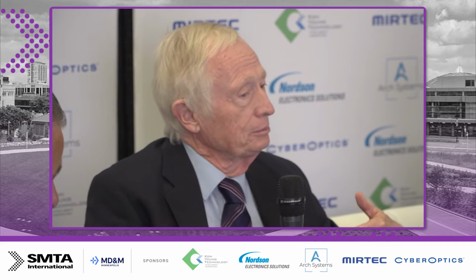And that's just really to establish the benchmark of where the current temperature threshold is that defines LTS, low temperature solders. Well, it's interesting. We had this discussion during an iNEMI project committee, and the first definition is anything lower than the temperatures you need for the established lead-free alloys, SAC 305 and SN100C and things like that. So if it's less than that, then we're in the LTS. But if you're looking at controlling warpage in IC packages, it looks like under 200 and ideally close to 180. So it depends what the application is as to how you define it.